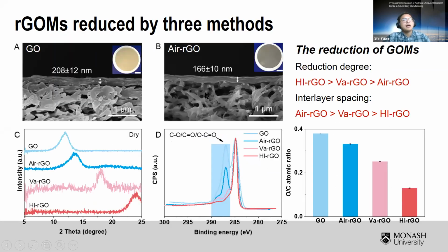Firstly, I investigated the structure through cross-sectional SEM images of GO and ARGO. We can observe the decrease in their thickness. We also investigated the reduction degree by XPS and the interspacing by XRD. By comparing the oxygen to carbon atomic ratio, ARGO shows the lowest reduction degree and largest interspacing, which means thermal reduction in air is a moderate reduction process compared with its counterparts.